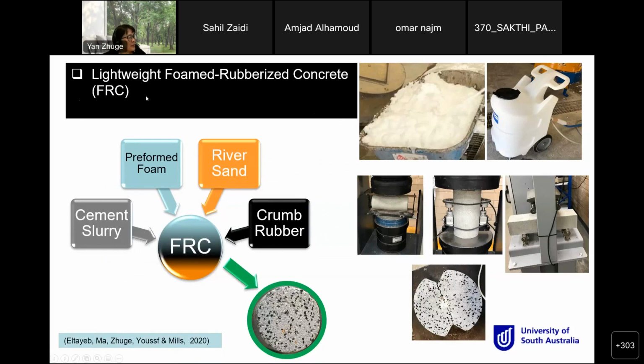So we try to make another product called lightweight foam rubberized concrete. We have the preformed foam; you see this diagram for the foam generator. We have river sand, crumb rubber to partially replace the river sand, and we also have cement. And we try to make a foam rubberized concrete. So that is the final product. We did all different testing: compression test, tensile test, and flexural strength test. All of this has been carried out.